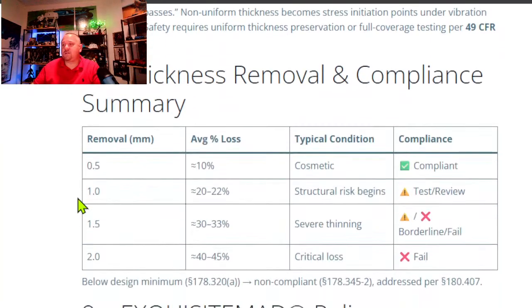So, thickness removal and compliance summary. This is removal in millimeters. If you remove half a millimeter, it's 10% loss. Typical condition is cosmetic after and is compliant. As soon as you get to 1 millimeter removal, you're removing 20 to 22%. Structural risk begins. Test and review. 1.5 millimeter removal is 30 to 33% loss of the structure. Severe thinning, borderline fail. Removal at 2.0, average loss is 40 to 45%. That is critical loss. It will most definitely always fail inspection.